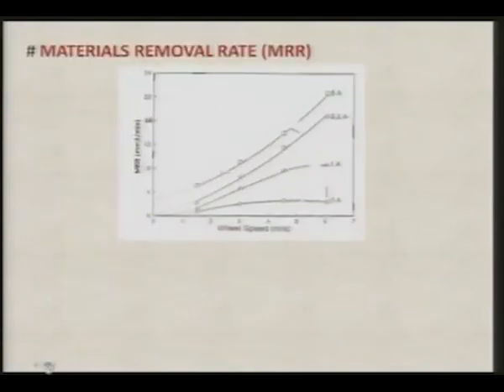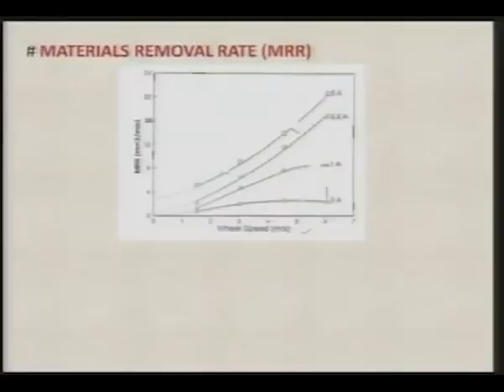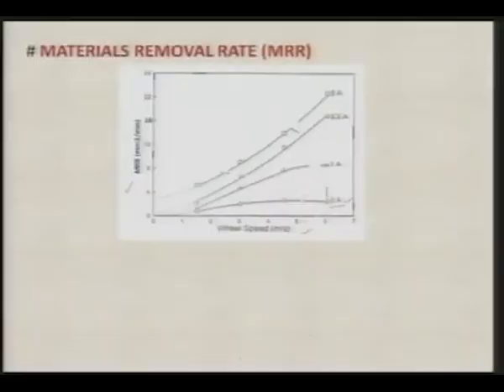Now, some experiments have been conducted by various researchers to evaluate the performance of the electric discharge diamond grinding process or electric discharge abrasive grinding process. Here you can see the main parameter is wheel speed, that is the RPM of the grinding wheel, and here is the volumetric material removal rate in cubic millimeter per minute. The important thing you can see here is that as the current is increasing, the volumetric material removal rate is increasing. Here is the 0 current, that means it becomes a normal grinding operation with the help of diamond wheel. So, you can call it diamond grinding, where you have 0 ampere as the current, but as you are increasing the current, the volumetric material removal rate is also increasing. Here is the 1 ampere, 2.5 ampere and 5 ampere.